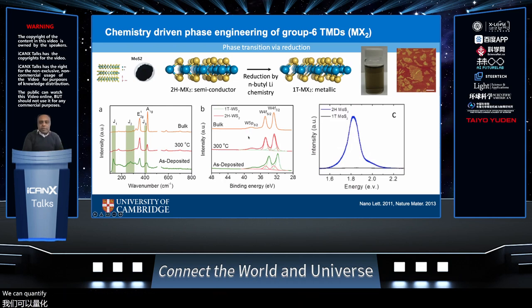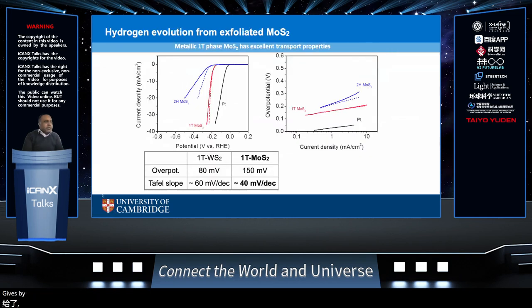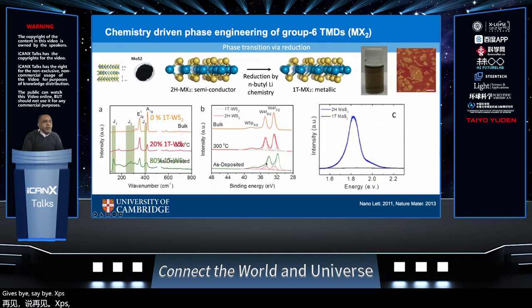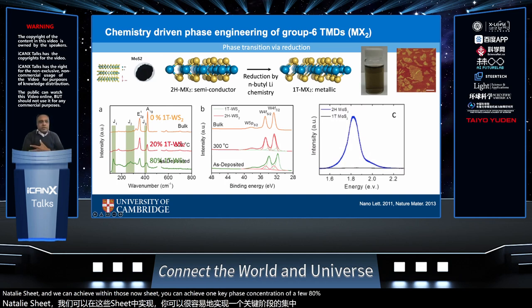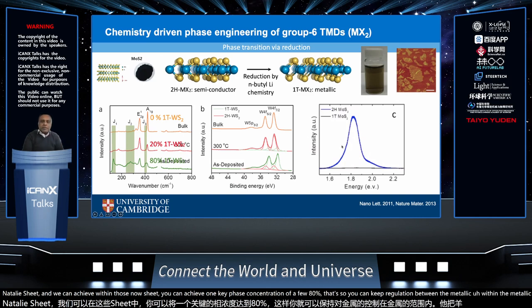We can quantify the amount of 1T phase concentration the reaction gives by XPS, where we can fit the different contributions of the 1T component and the 2H component, and obtain the fraction of the 1T phase concentration. So when we do this reaction, we typically have sheets of MoS2 nanosheets, and within those nanosheets we can achieve 1T phase concentration of up to 80%. So you have complete percolation within the metallic phase to render the sheet metallic.